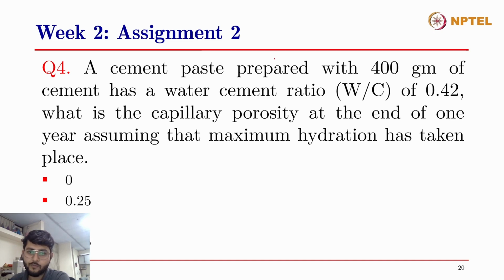Moving on to the fourth question. A cement paste prepared with 400 grams of cement has a water to cement ratio of 0.42. What is the capillary porosity at the end of 1 year, assuming that maximum hydration has taken place? The catchy phrase here is maximum hydration has already taken place. So the cement paste is prepared with 400 grams of cement and has a water to cement ratio of 0.42. What is the capillary porosity at the end of 1 year, assuming that maximum hydration has taken place?